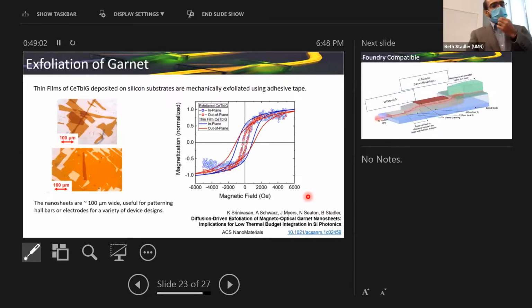We did some optical microscope imaging where we see that we are able to exfoliate them into these beautiful large nanosheets, about 100 microns wide, and they're sufficiently large enough to transfer print them on waveguides or even pattern hall bars and electrodes to do spin transport measurements.